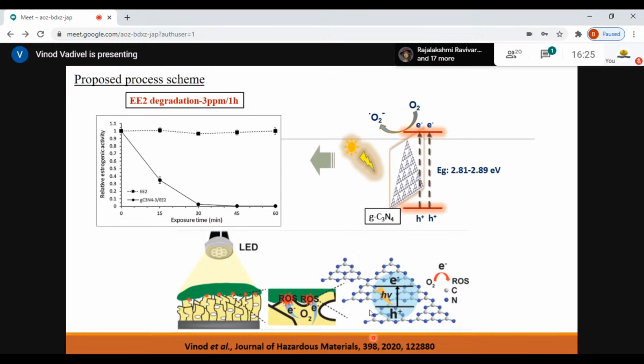So the proposed scheme is like this. We can take this GC3N4 material, a carbon nitride material. We modify the band gap for our solar system, and you make your EE2 degradation based on different modifications. You can see the kinetics changes. With the GC3N4, it's almost 30 minutes that it's degraded, and we have also found the degradation pathway of this particular system with complete mineralization. The whole work can be found in this particular journal which we published in 2020 in Hazardous Materials.